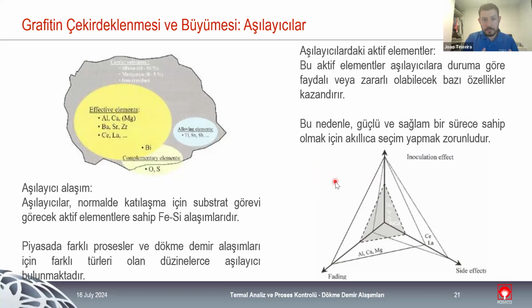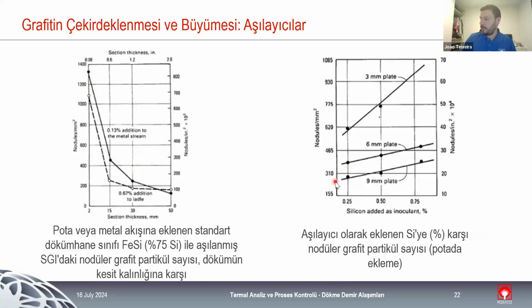So there are dozens of different inoculant agents in the market, and all of them have some positives and some negatives, even if it is the price, improvement of mechanical properties. Some inoculants are more specific for gray iron, for example, with the strontium ones. Lanthanum is really good, but as mentioned, the fading resistance is lower. Cerium is really good, but in some particular cases, it could be harmful to the production of nodular cast iron. So we really need to play with all the different types of inoculants that we have, and we need to be careful with the ones that we choose, because there are dozens in the market, and most of them have different applications for production.